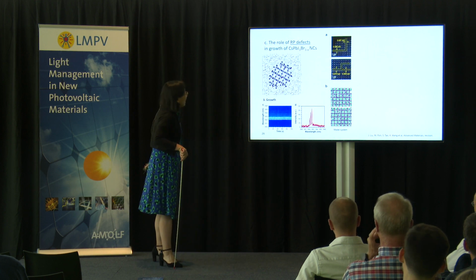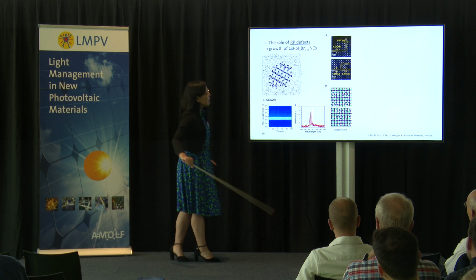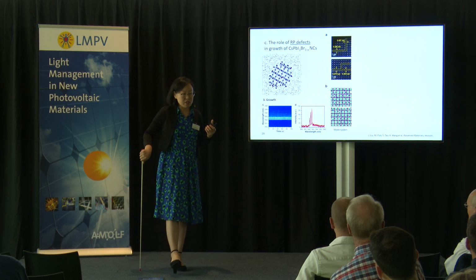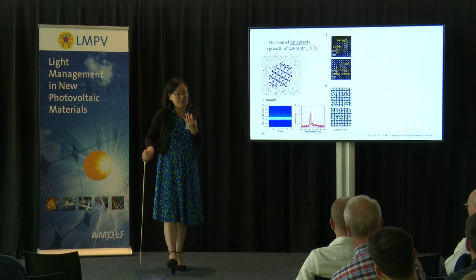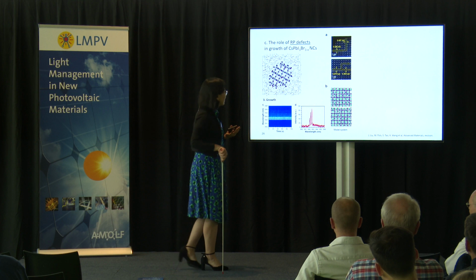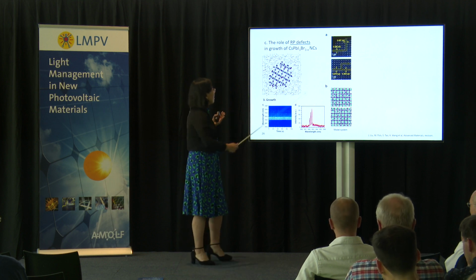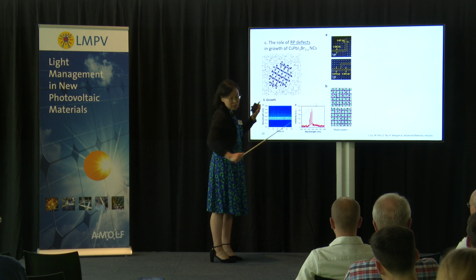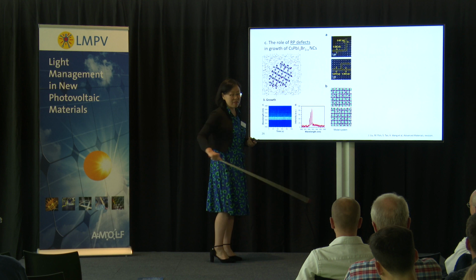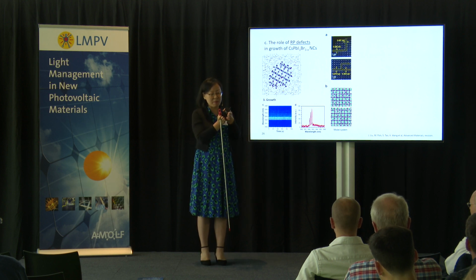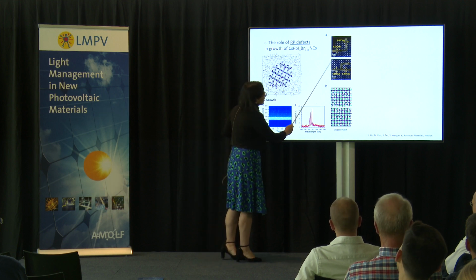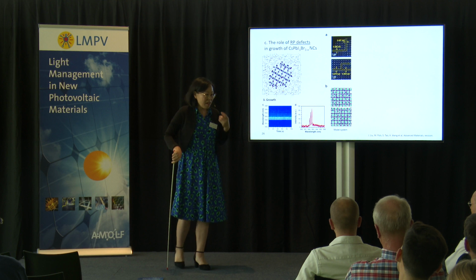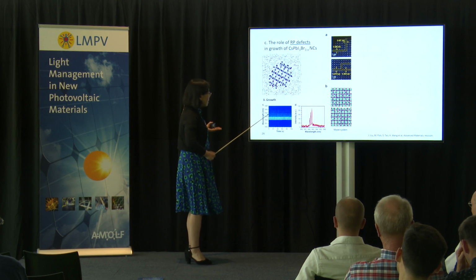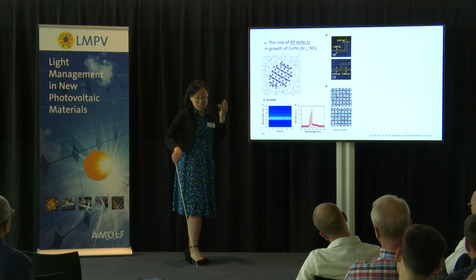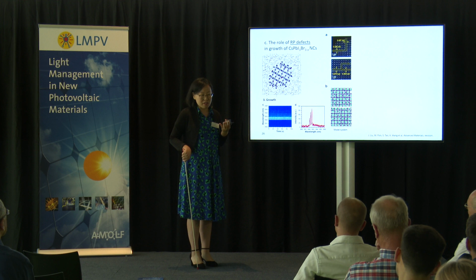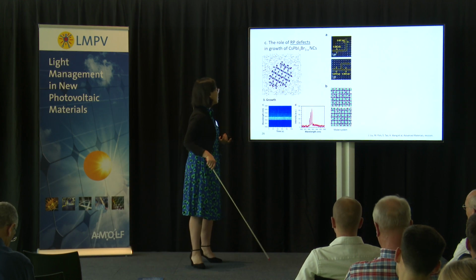Okay, last example. This is a cesium compound with mixed iodine and bromine. This is a nanocrystal made in the lab with quenching, needing a lot of extreme non-equilibrium growth conditions. One interesting thing about the growth is that in the high resolution TEM or STM image, we see an RP kind of defect. That means the lead iodide planar bit shifted, and this defect is terminated by cesium iodide or cesium bromine termination. What is interesting about it is that this film allows us to obtain discrete domains that give discrete emission or absorption, which allows us to manipulate this purity for quantum application.